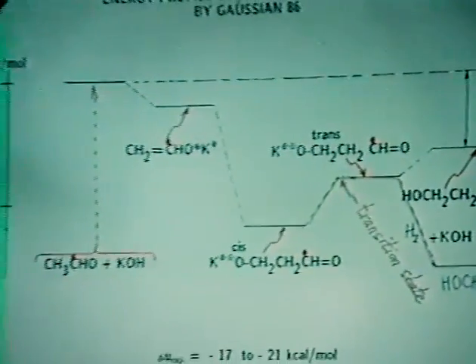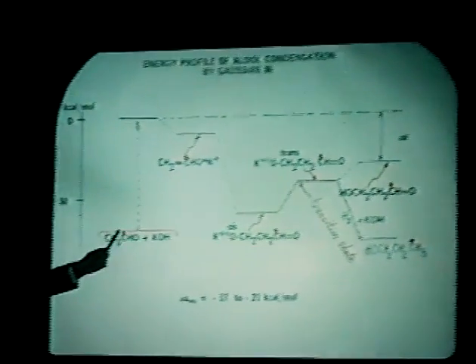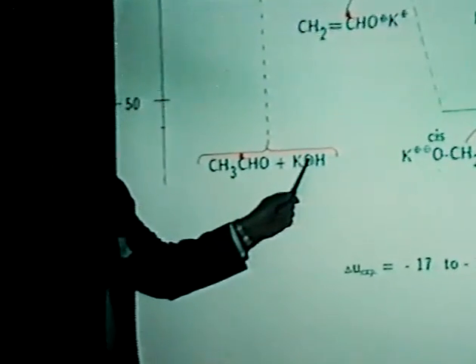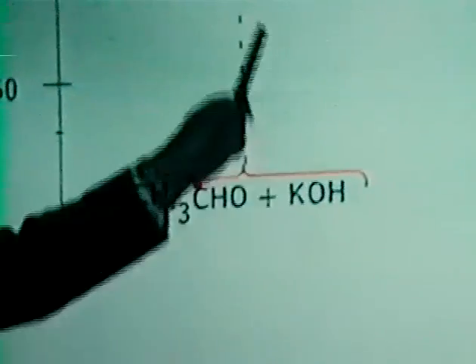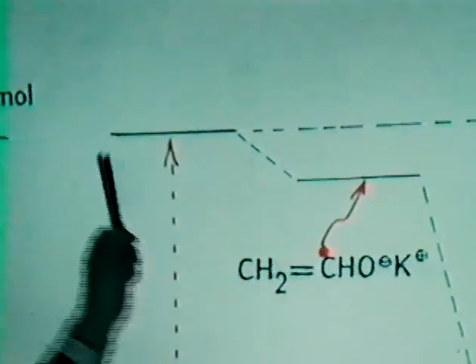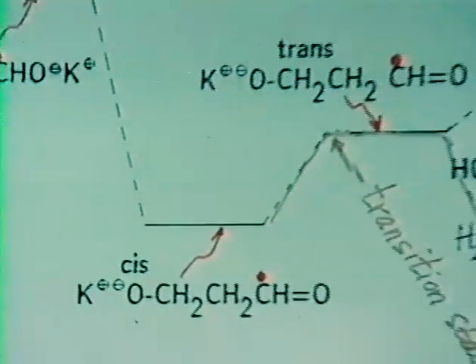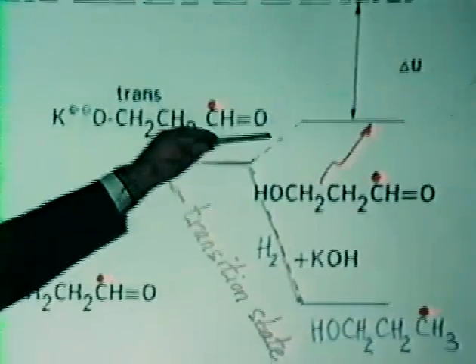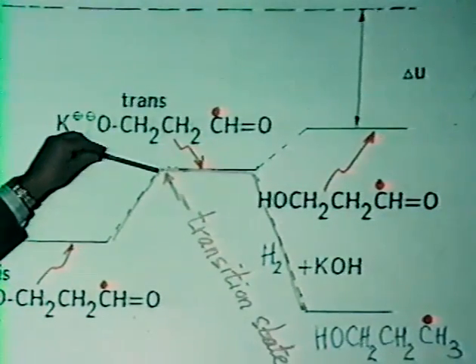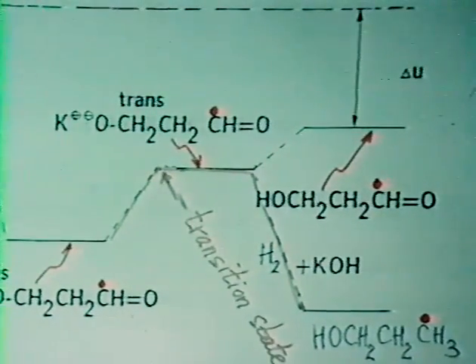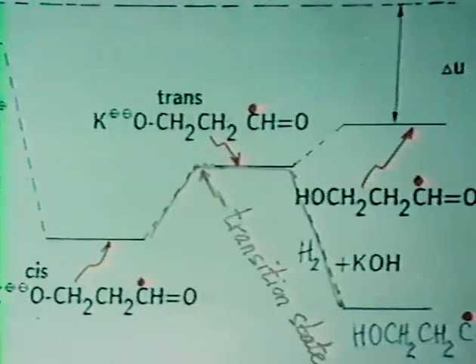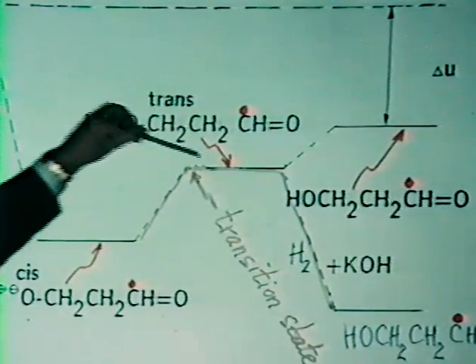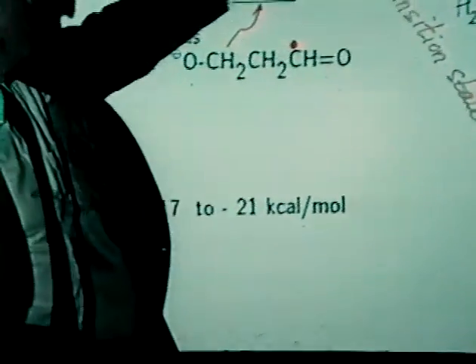If we then summarize the whole energy profile of that kind of aldol condensation, we first react acetaldehyde, labeled here, with potassium hydroxide or cesium hydroxide, rubidium hydroxide, whatever. We make the enolate or carbanion with this amount of released energy. Then we make the cis configuration of 1,3-ketoalkoxide, which is transposed into the trans configuration, costing this much energy. In fact, we calculated the transition states here, identified them by the usual criteria, and found that the transition state is close to the trans configuration. Essentially, the trans isomer is the transition state. There's only a small energy difference.